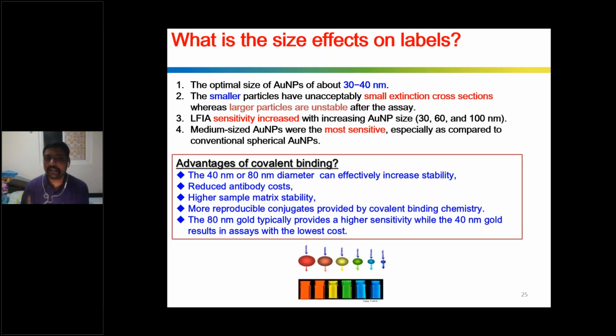And then the LFA sensitivity increases with increasing nanoparticle size. The nanoparticle sizes can be varied from 30 to 100 nanometers, but the most sensitive range we have identified and optimized is 30 to 40 nanometers. And what are the other advantages when we use this type of labeling material?